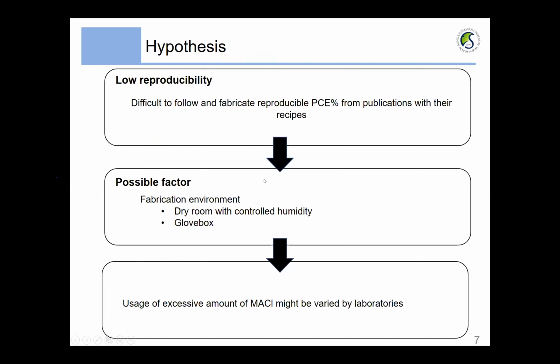We also noticed that the suggested amount of MACl varies across many publications, and the fabrication environment is often insufficiently provided in many papers. So we suggest the conjecture that humidity might be a main cause for the low reproducibility of the MACl additives. Because many labs occupy different facilities with different humidity levels, we thought that humidity might be a critical factor for determining the MACl content.